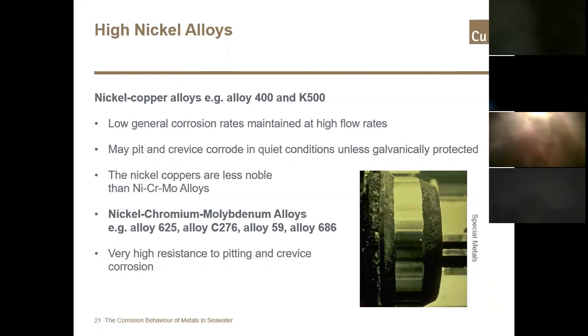Cathodic protection can be used when in contact with less noble metals, and this would enhance the performance of these alloys. But at velocities greater than 1 meter per second, same as the stainless steels, the surface would remain passive and offer a good resistance to corrosion. But you would need to be aware of materials in the same alloy system, as the nickel coppers are less noble than the nickel chromium molybdenum alloys and high alloy steels. So if they were coupled with these, then there could be issues.